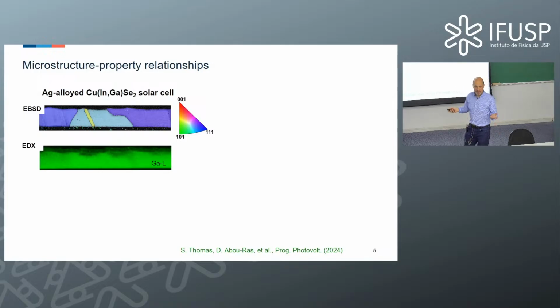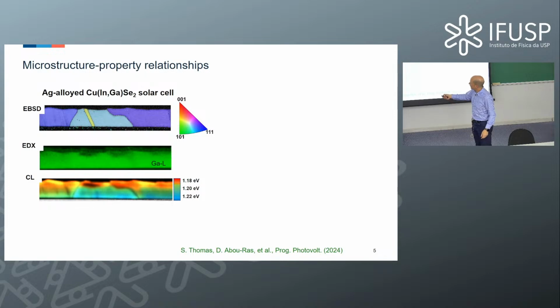And this you can corroborate by acquiring, not energy dispersive X-ray spectroscopy, but cathodoluminescence maps. If you look at the distribution of the peak emission energy, you can see that there's a distribution of phases. Copper indium diselenide has a bandgap energy of roughly 1 electron volt, and copper gallium diselenide has a bandgap energy of about 1.7 electron volts. This is why from these emission energies you can deduce a local gallium to indium ratio.